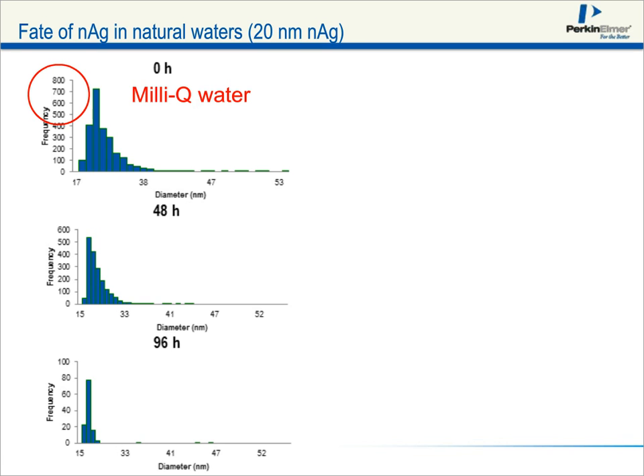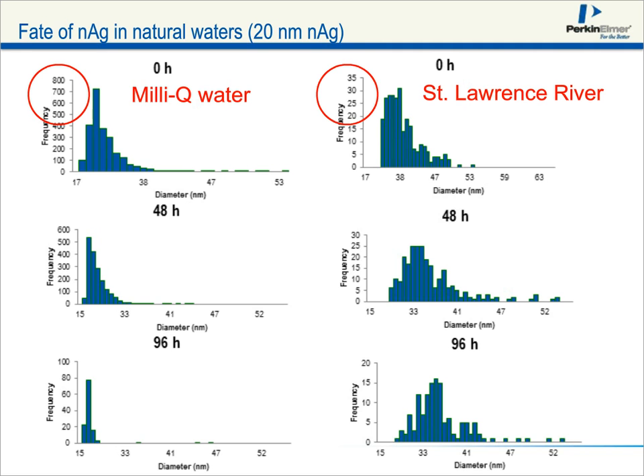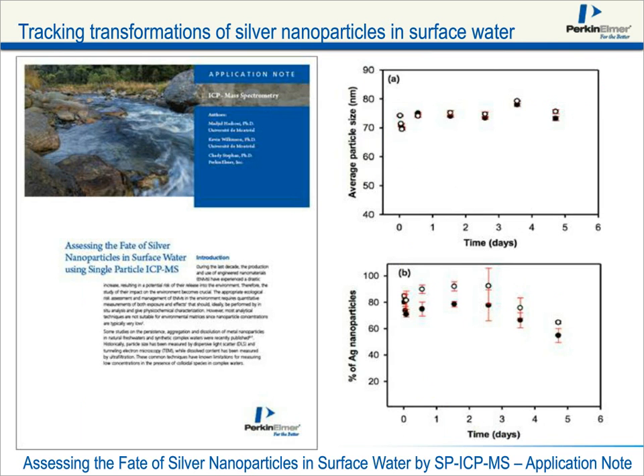If we look now in a natural water with this more complex matrix, what you're seeing is actually going slightly in the other direction, seems to be getting more polydispersed samples, probably related to agglomeration of the sample. We are seeing a decrease in the particle concentration, but you're getting a shift more to the right. So again, part of this problem is related to the matrix, and if you're interested in seeing a little bit more on the transformations of the silver nanoparticles, you can go into this application note that we produced a little while ago.